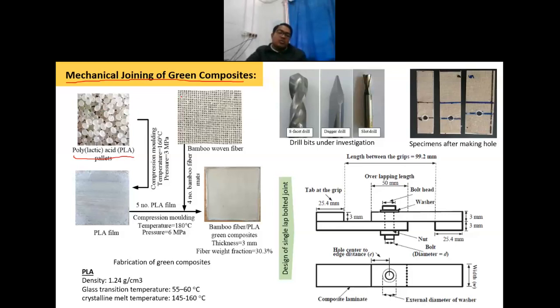So we have used a biodegradable polymer, and this is, you can see, fiber. This fiber is in mat form, that is, in woven mat form. That means my fibers are oriented in 0 degree and 90 degree directions. Okay, so you can see in both directions fibers are available. This is called the woven mat. So we have used this bamboo fiber and polylactic acid. Both are biodegradable in nature, so the resultant composite material is a fully green composite material.